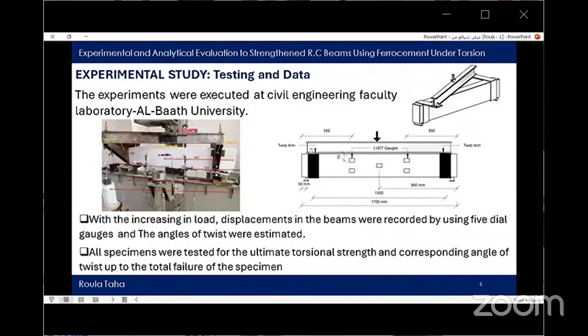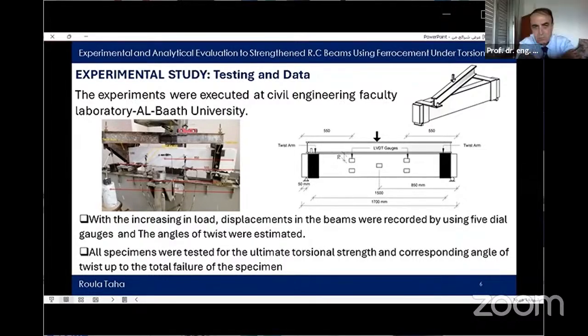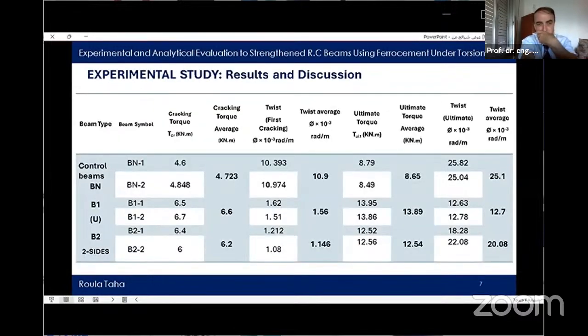All the tested beams were subjected to twist from both ends using two opposite twist arms. 5 sensors were installed to record displacement as the load increased. Then the angle of twist was calculated. All beams were tested to determine their cracking torque, ultimate torsional strength, and angle of twist when the first crack appeared and at the failure point. From the following table, we can see that cracking and ultimate torque of strengthened beams B1 and B2 considerably increased in comparison with the control beam, while the twist angle value significantly decreased.